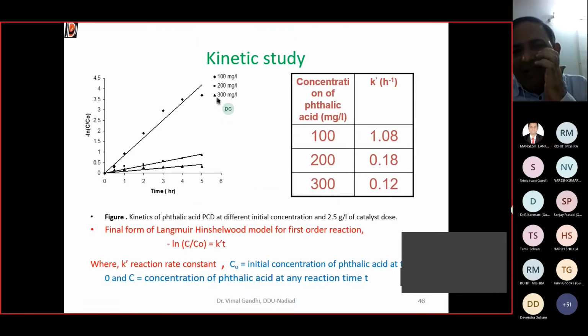And the kinetic study follows a Langmuir-Hinshelwood first order reaction, and we tried to find the K value, the reaction rate constant, also for phthalic acid. Apart from that, we carried out one experiment for phthalic acid, nitrobenzoic acid, chlorobenzoic acid, and benzoic acid. And we observed that in a bare solution of phthalic acid with a fixed dose of TiO2, 4.5% is adsorbed after 1 hour, that is the highest, and the least adsorbed is benzoic acid. Now, what is the significance of this value? You will understand after one slide.